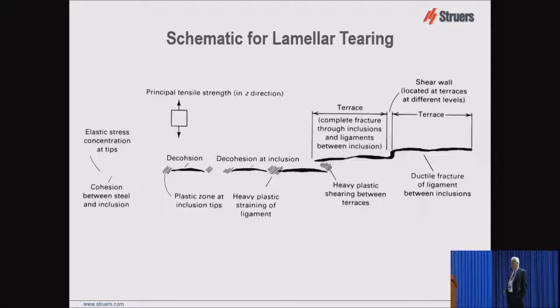Now, there's another classic failure problem in the literature, and I've actually been involved in a couple of these cases, called lamellar tearing. And this is a schematic of the process. We have an elastic stress concentration at the tips of this crack, and inclusions. Sometimes these follow sulfide inclusion stringers, but this is an inclusion here, or sulfides, and we've got high stress at the tips, and then it starts cracking and linking together, and eventually the whole piece falls apart.